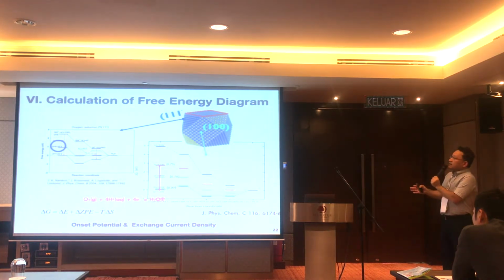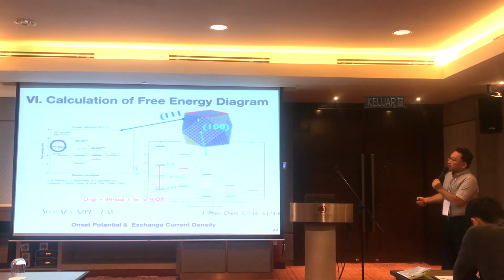But the activity of the platinum nanoparticle catalyst material actually depends on the electrode potential, and also on the facet. This picture shows that a typical nanoparticle has two different facets, one on the 111 surface and one on the 100 surface, and there's an edge between them. This picture shows that platinum 111 surface, this triangular type facet, is much better than 100.